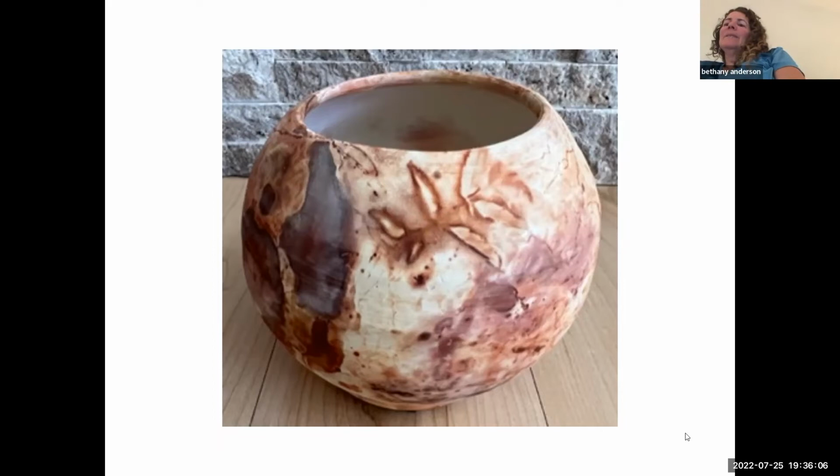You know, my pieces were bisque fired to 04 since they were fired at school. But Don and Randy told me they only bisque fire all of this stuff to 08 because they think it absorbs their glazes better. Okay. Interesting.